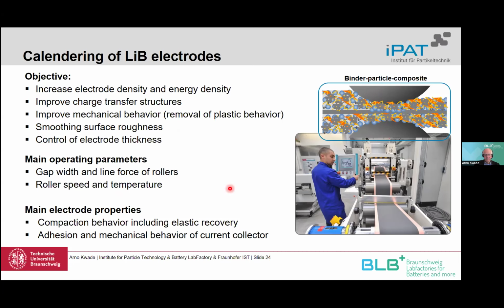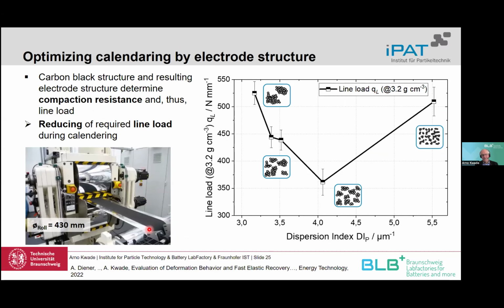Rachel will also talk about it a little bit more later. But there is also elastic recovery, as you maybe know from tableting, and this elastic recovery hinders our calendering process. One single result I want to show you, because it relates to what I showed regarding the dispersion or comminution process, is that the dispersing of the carbon black is also decisive for the calendering process. For small dispersion indexes, where we have a lot of agglomerates, the line load is much higher to come to the final result.